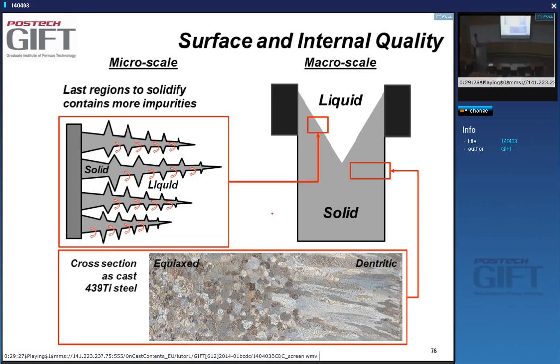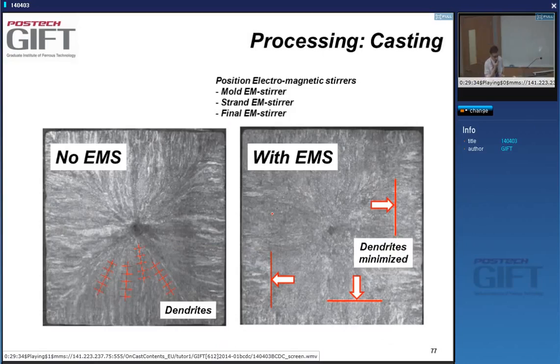So that's why we will add these stirrers. This is an example here. It's a square billet, not a slab. This one is cast without an EMS, and you can see this patterning here, which are dendrites. There are large dendrites. If you have an EMS in the line, you can minimize the growth of these dendrites, and you can also see that the center line segregation is much lower. So your billet is more homogeneous.